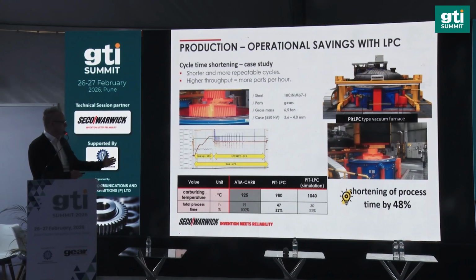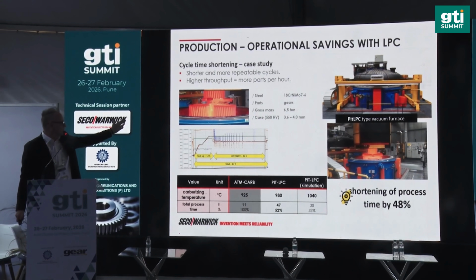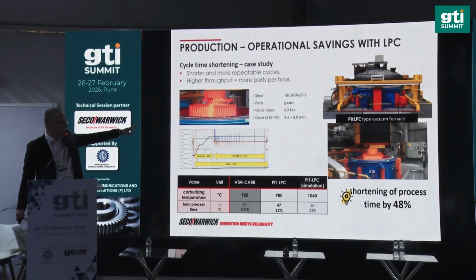The recent development of ours, referring to the pit type furnaces, more dedicated for large parts, reaching 1.2, 1.8, 2 meters in diameter and a depth of 3 meters. In this particular case, we were carburizing the gears for wind mill systems, and the gross charge was 6.5 ton. And the case reaching up to 4 millimeters.